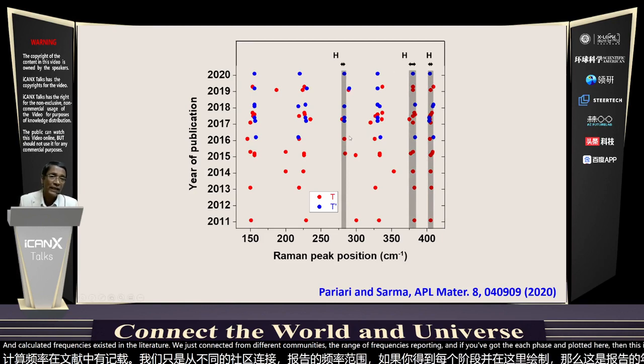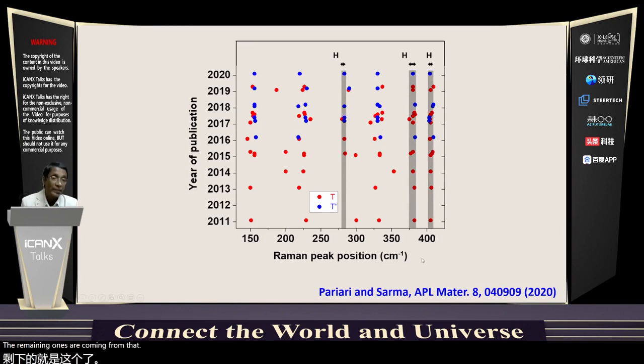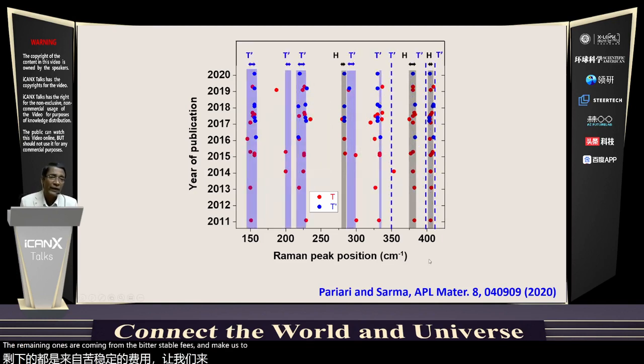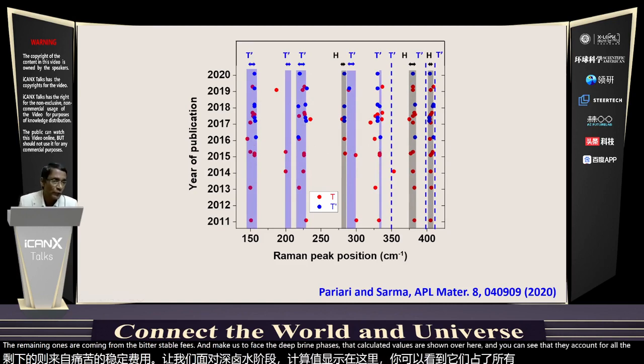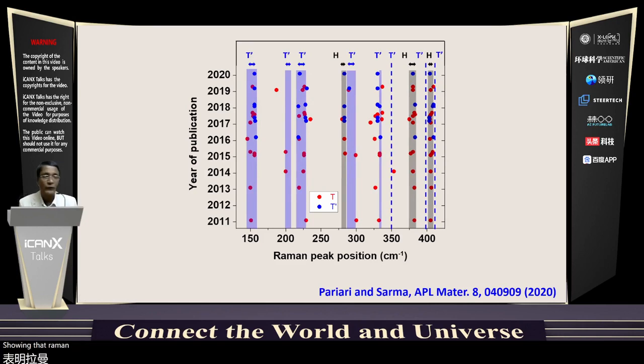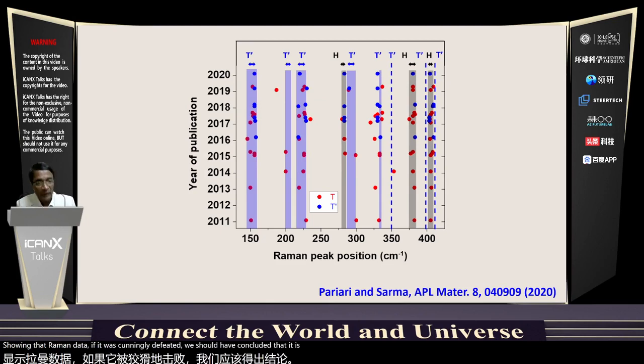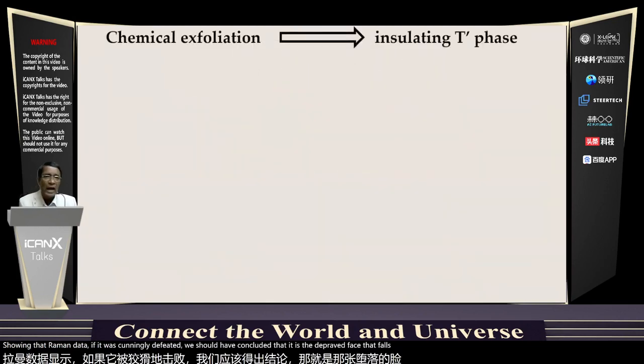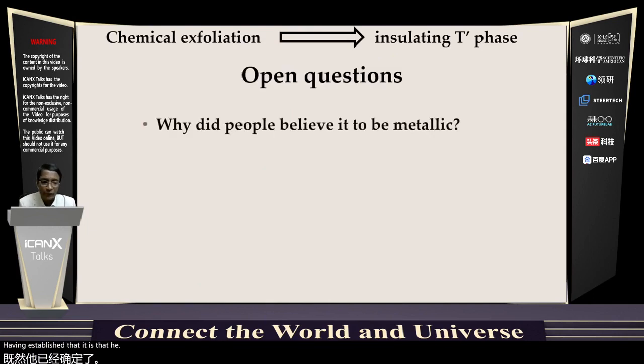So those are the H phase signals. The remaining ones are coming from the metastable phase, and for the metastable phase, the T prime phase, the calculated values are shown over here. And you can see that they account for all the Raman frequencies that have been reported, showing that if the Raman data was correctly interpreted, we should have concluded that it is the T prime phase that forms.